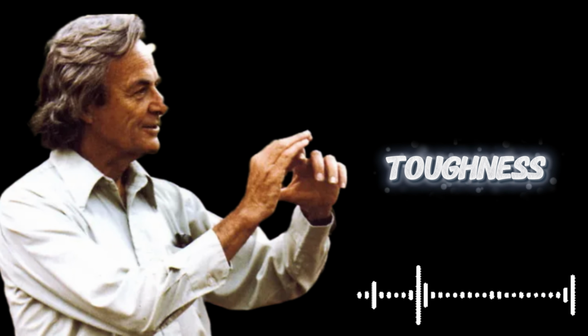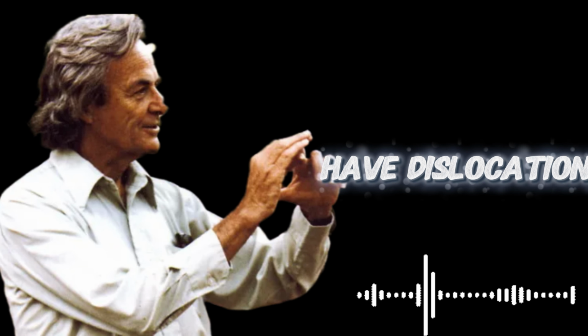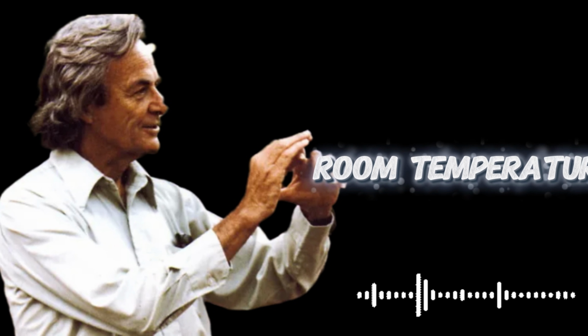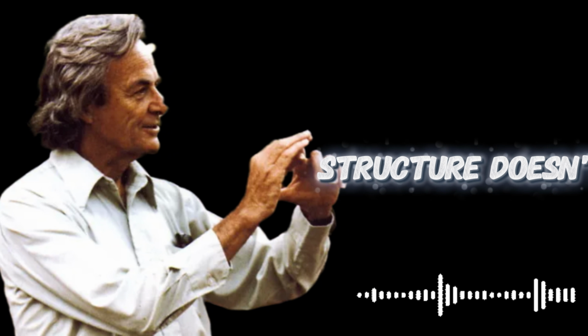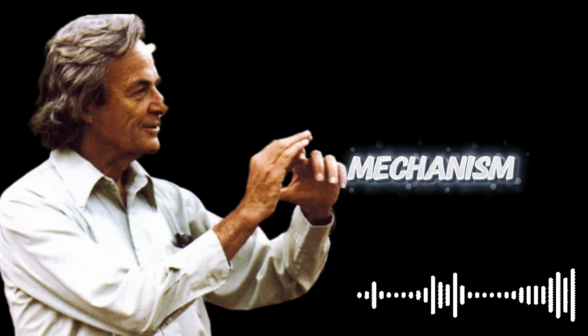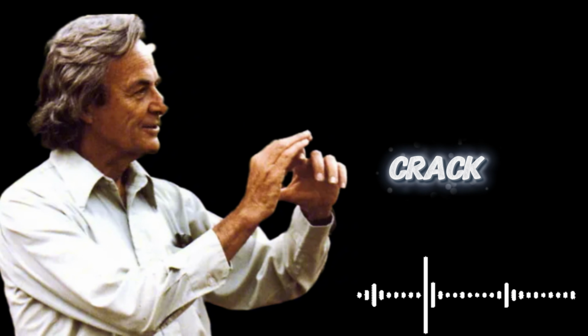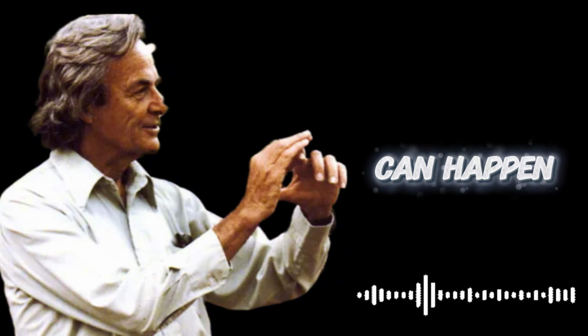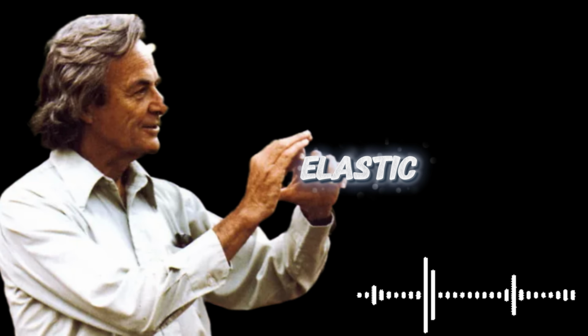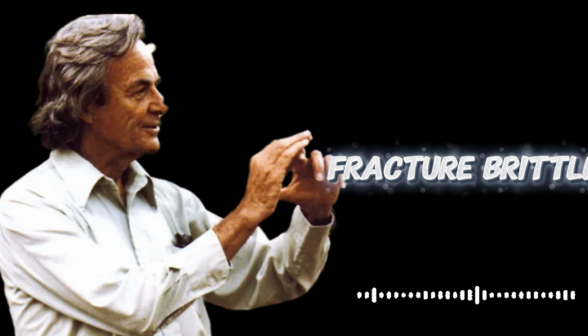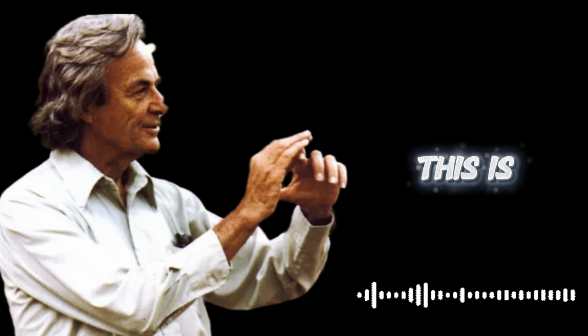That's toughness. Glass doesn't have dislocations that can move at room temperature. The amorphous structure doesn't have slip planes. There's no mechanism for plastic deformation. So when stress concentrates at a crack tip in glass, the only thing that can happen is bond breaking, elastic deformation up to the point where bonds snap, then catastrophic fracture, brittle failure. This is why glass is strong but not tough.